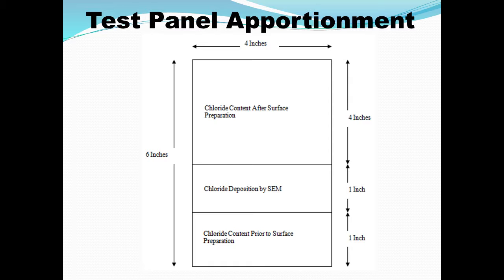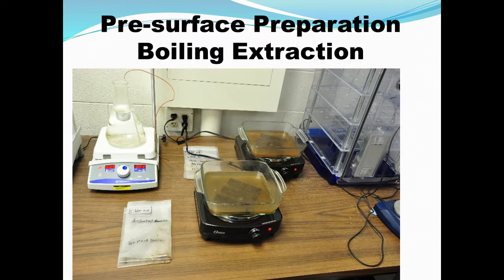After clipping that 1-inch off, they were then subjected to the various surface preparation methods. As you can see, after the surface preparation, it was divided again. One piece was for analysis by scanning electron microscope, this 1-inch slab, and then this 4x4 piece, again with boiling extraction, to measure the quantities of chlorides. These were one set of 3 panels that was going to have a particular surface preparation method. You can see where the 3 pieces are clipped off, and they're in boiling extraction.